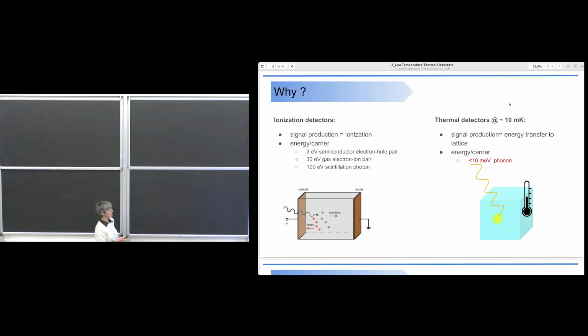Allora, in the first case, ionization is the primary mechanism of producing the signal. And you produce a number of, let's say, energy carriers or signal carriers, as you prefer, that depending on the specifics of the technology require a different amount of energy to be produced. For example, in a semiconductor, you need about 3 electron volts to produce an electron-hole pair. If you move to a technology based on gases, you need 30 electron volts, and if you are using a scintillation mechanism, typically an inorganic crystal, you need about 100 electron volts.